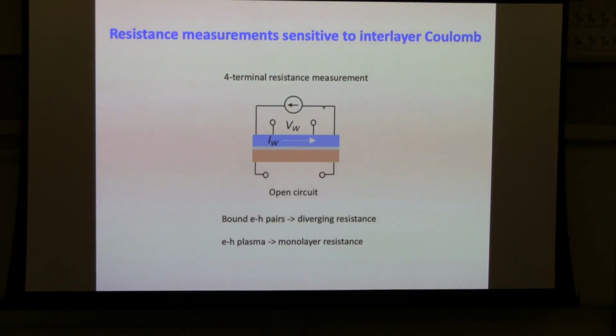All right, so let me tell you another measurement method, where we perform a standard 4-terminal measurement in the tungsten layer, while leaving the electron layer open circuit. In this measurement, if there is no interlayer Coulomb interaction, then this 4-terminal measurement on the hole layer will be just the hole transport of the monolayer. There's nothing surprising. For instance, if it's in the electron-hole plasma regime with negligible interlayer Coulomb interaction at low temperature, that would just be the monolayer resistance. On the other hand, if you have some bound states formed between this hole layer and the electron layer, then you will get a diverging resistance at the low temperature limit because the electrons are not allowed to flow.